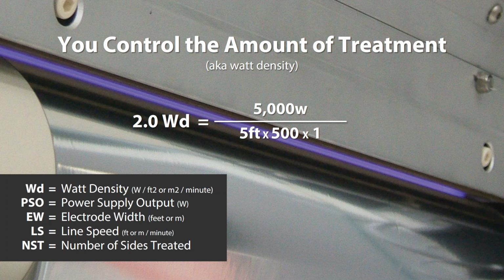So you might be asking, well, that sounds great, Tom, but so what? Well, this is how all corona treaters are sized. I don't care if the corona treater is a ceramic electrode corona treater. I don't care if it's a bare-roll corona treater or metal electrode corona treater, or for that matter, an atmospheric plasma treater. These are all sized in the same fashion. They're done the same way. As a general rule of thumb, most corona treaters supplied today are sized somewhere between 2 and 3 watts per square foot per minute.